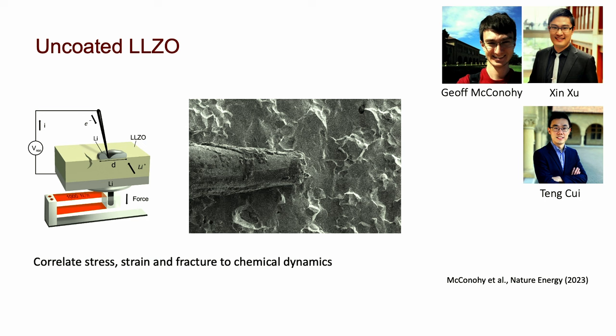In previous work that our two labs have collaborated on, we've used in situ SEM, scanning electron microscope imaging, to look directly at the failure processes at the microscale level, where the most interesting features form. This is a device where we have our LLZO on top of lithium, and behind that is a force sensor. On top of that, we have both a mechanical probe and an electrochemical probe. Through that, we form a very localized circuit.